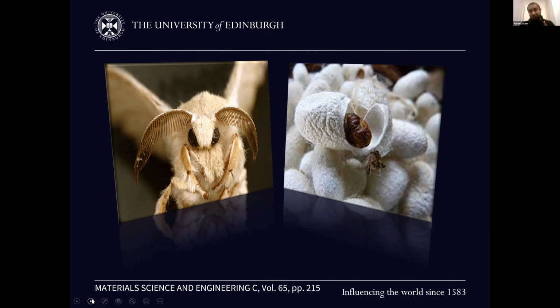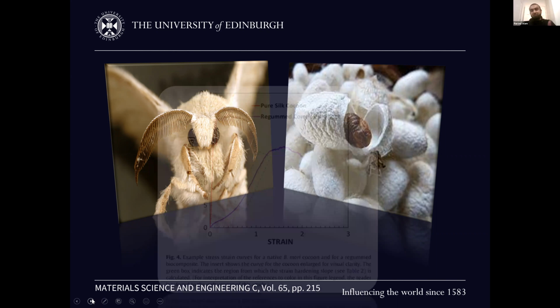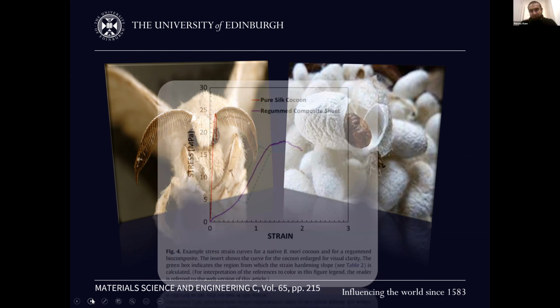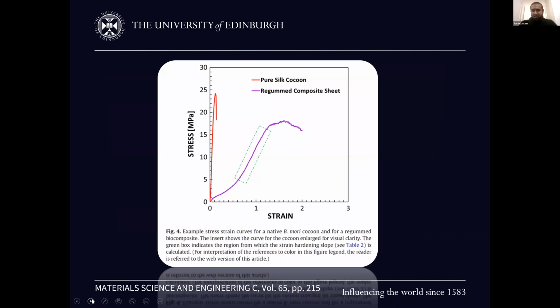Now, this is very interesting, because we did this and then we tested them, and we got a really interesting result here. This is not one result. There's obviously repeatability. I'm just showing you representative curves, but we do lose about a third of the strength if we do that. Quite a lot of stiffness, but we do massively increase the strain to failure to 200%, and therefore we massively increase the toughness, or the mechanical energy absorption that is possible with this kind of material.